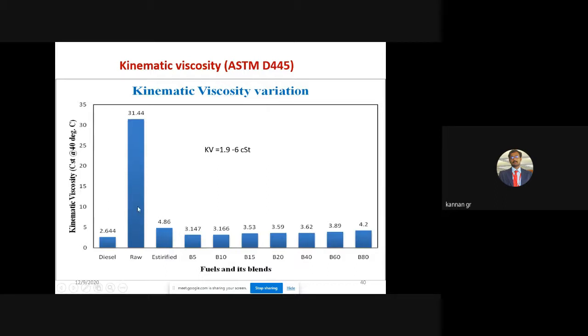You can see the raw palm oil. We can use raw palm oil as a feedstock or fuel for an engine, but it has a higher viscosity, so it will affect the fuel characteristics and fuel spray patterns. But when we go for transesterification, it is reduced to 4.86. So the viscosity is reduced with the help of the transesterification process.